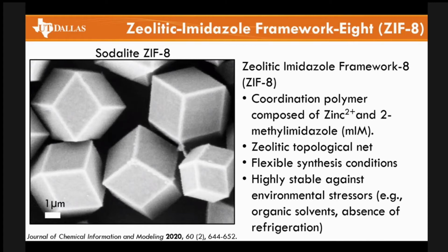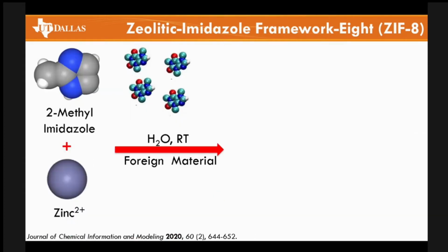This is a coordination polymer constructed from the tetrahedral interaction between zinc and 2-methylimidazole. It is a porous material with flexible synthetic conditions. It's highly stable. And very interestingly, a lot of research has used Zeolitic Imidazole Framework 8 to stabilize a wide variety of proteinaceous materials. The way that the reaction is carried out is quite simple. Again, we have 2-methylimidazole and zinc acetate. As I was saying earlier, the synthetic conditions are quite flexible. That means that the synthesis can be carried out at room temperature using water as a solvent. It doesn't get any more protein friendly than that.